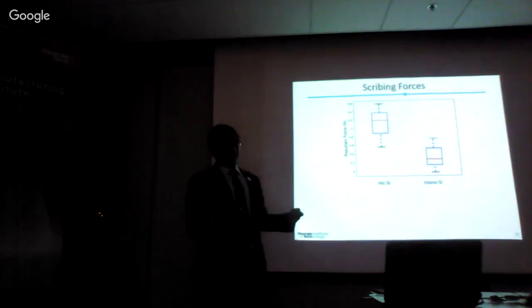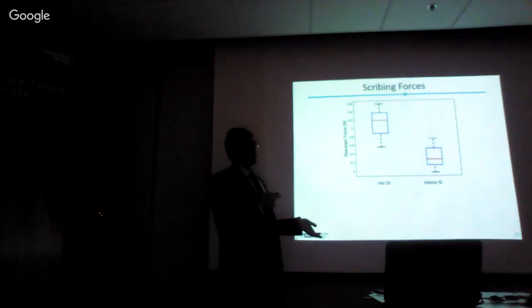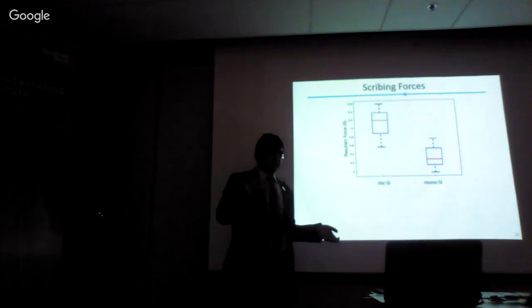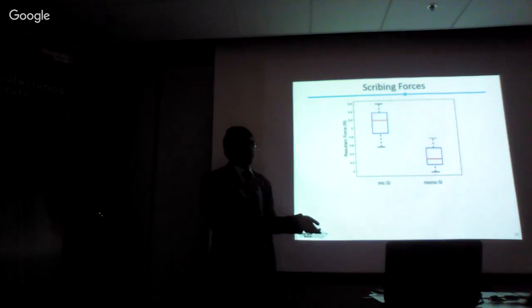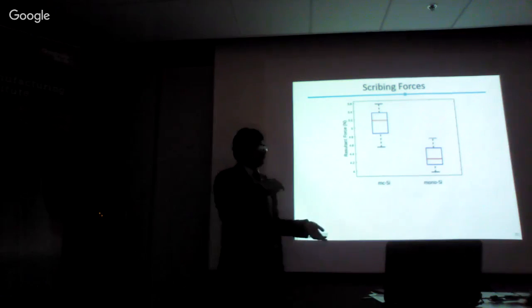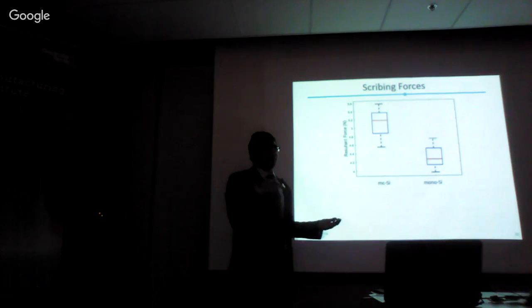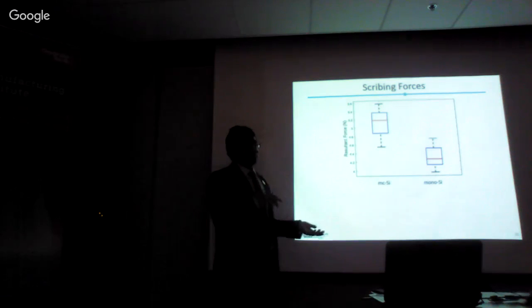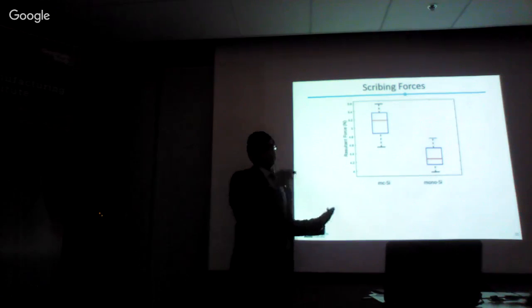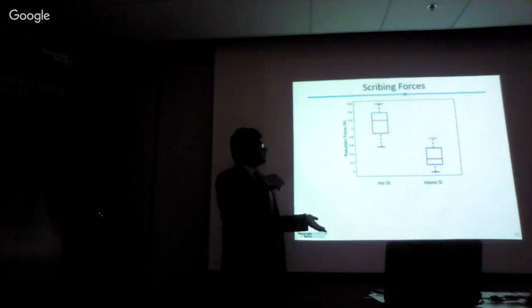For the scribing forces, here I plotted the resultant forces across all the scribes I did for multi-crystalline silicon and for monocrystalline silicon. We find that in the box plot, the average forces for multi-crystalline silicon are consistently higher compared to the average forces for monocrystalline silicon. And there is some scatter, with some high forces and some low forces.